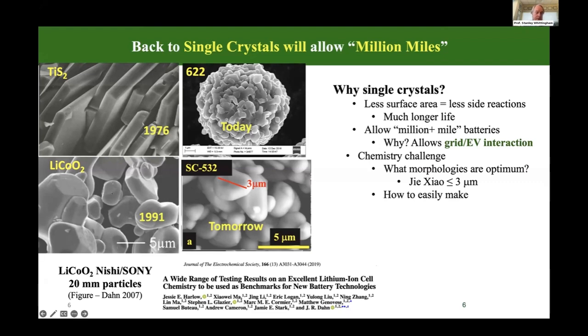Sony, when they made lithium cobalt oxide batteries, also wanted to use very large particles. And this should say this is 20 micrometer particles. This particular picture is one of Jeff's, but the real Sony cells were about 4 or 5 times this size. But over time, people wanted higher and higher power densities, and we went to this meatball configuration where the large particles are probably about 5 to 10 microns across, and the primary particles are about 200 nanometers. So this increases the power density. There's been a push lately to go back to single crystals to reduce the reactivity, and Jeff has been a champion of this.